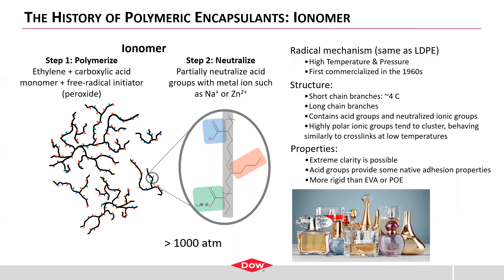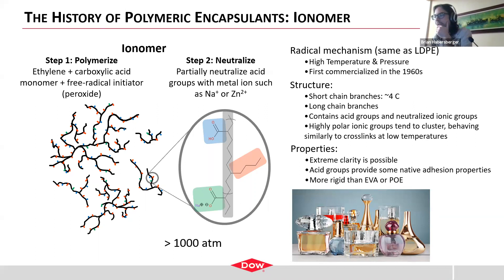Keeping on the ionomer theme — the question is how an ionomer could be a sodium barrier if it actually contains sodium, or are you referring only to ionomers with zinc ions as the neutralizer? In fact, it can be a sodium barrier even if it has sodium. The issue is that the sodium needs to be immobile more than it needs to be absent. I do suspect that out of concern toward the potential of sodium migration, the more likely choice would be to use a zinc ionomer. But in principle, a sodium-containing material can still be a sodium barrier.